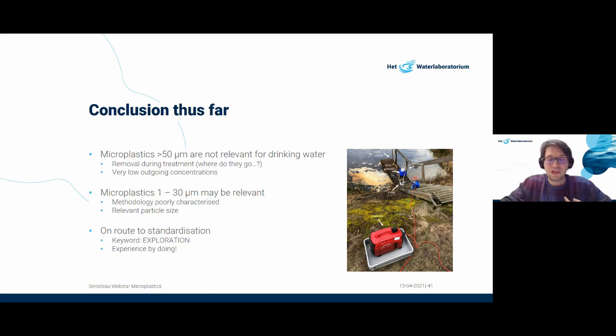On this part, I'm actually disagreeing with the previous speaker who said these methods are quite standardized. I think we still have a long way to go before we can actually compare these results properly. So the key message is that en route to standardization is exploration. Experience by doing: just by performing these analyses and samplings, you learn a lot about the do's and don'ts of sampling, and you don't get those from a theoretical assessment. You just find out that actually applying monitoring is a lot more difficult than developing the method for it.